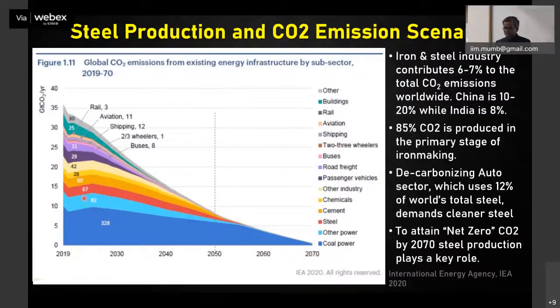And if you look here, 6-7% of it is, I think, gigatons of CO2 per year from the steel plants. So the iron and steel industry is producing about 6-7% average CO2. China produces about 10 to 20%. India is producing about 8%. And 85% of the CO2 is coming from the primary steel making process, the blast furnace, basic oxygen technology, which uses heavily coal. For every ton of steel, we use about 750 kg of coal.